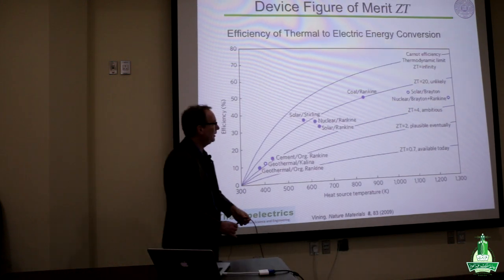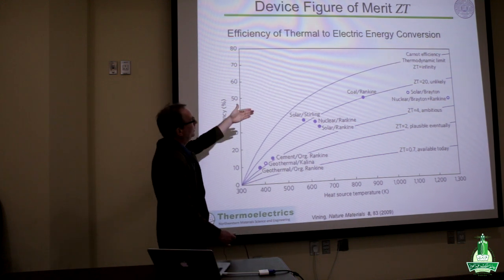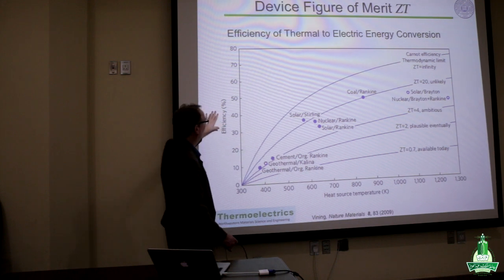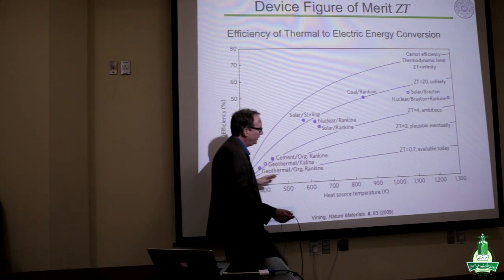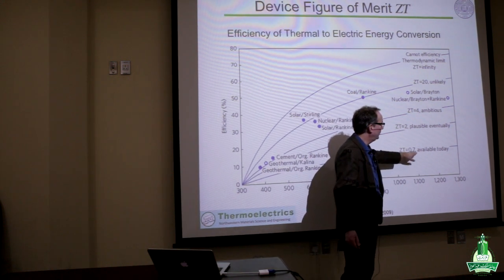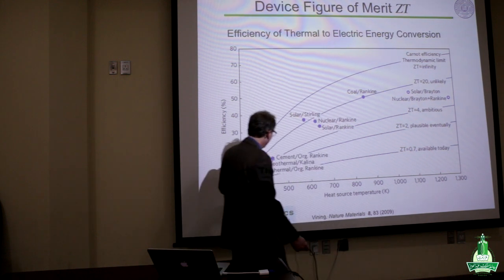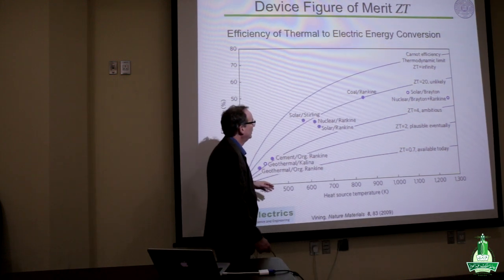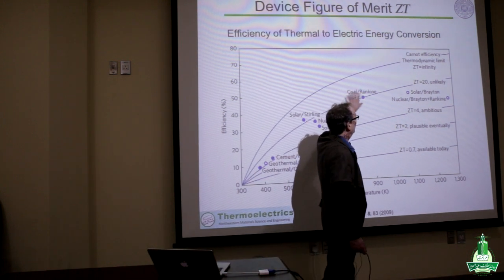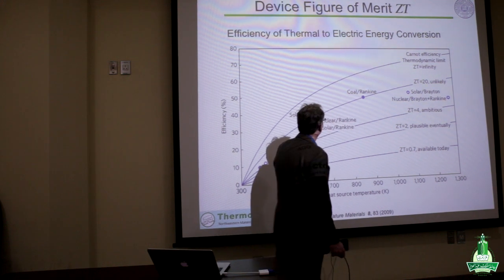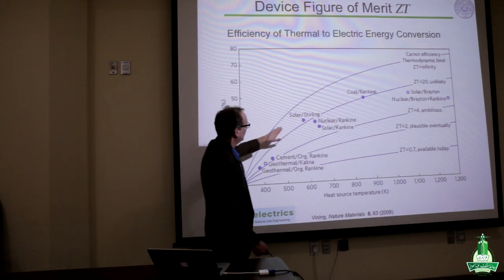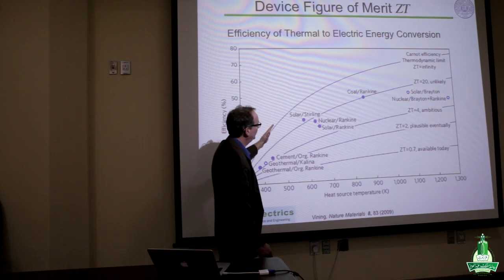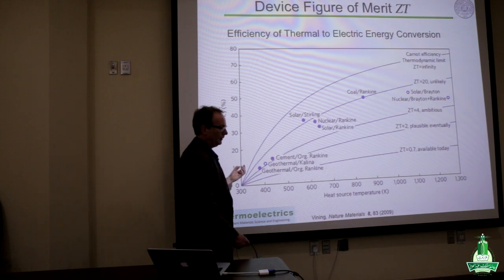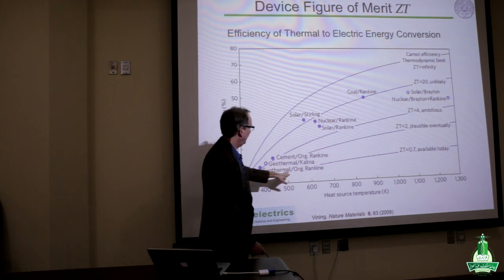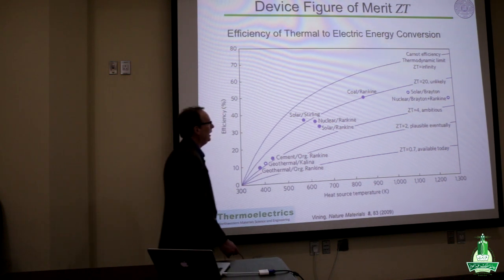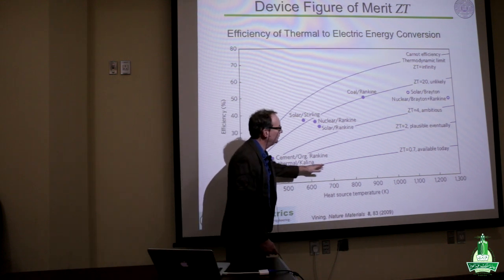All right, so to give you an idea, now that we can do this comparison as to how thermoelectrics compare to other systems in terms of efficiency, right now we typically have ZT parameters on the order of about 0.7, so less than 1, which means our efficiencies are relatively low compared to the large electricity producing systems such as the Rankine systems used for coal or Stirling systems. And as we move to smaller size systems such as organic Rankine, even those systems tend to have higher system efficiencies than what we get with thermoelectrics.